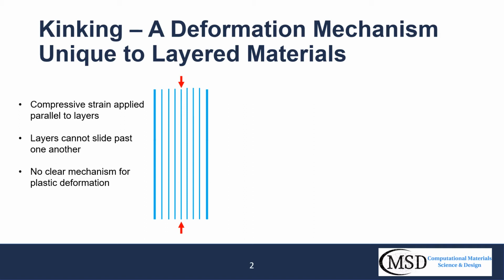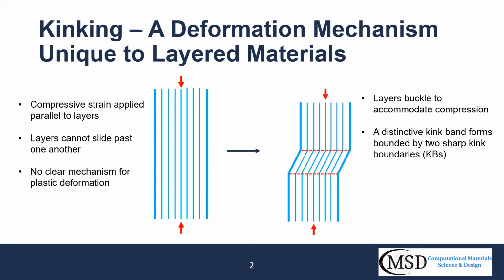But what we observe is a buckling of the layers to accommodate compression, thereby converting expensive in-plane strain to cheaper out-of-plane strain. Rather than a continuous elastic buckle, however, a distinctive kink band forms bounded by two sharp kink boundaries.